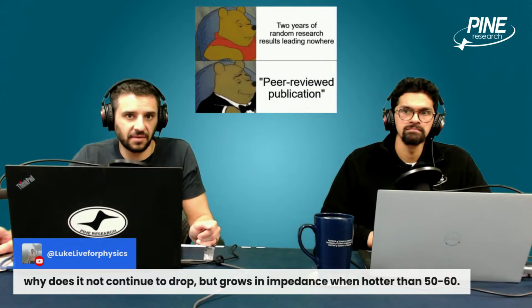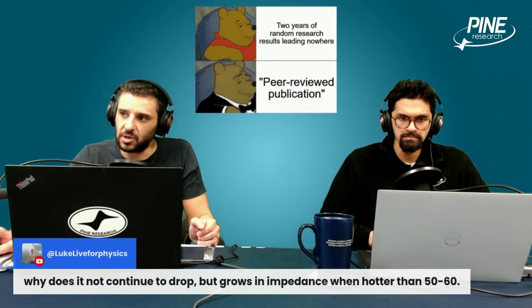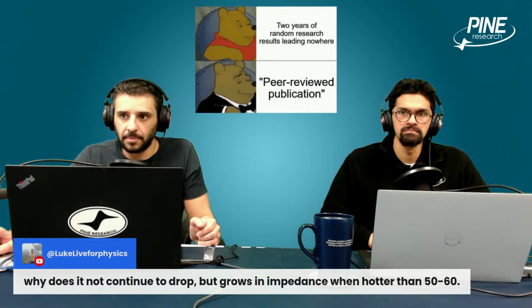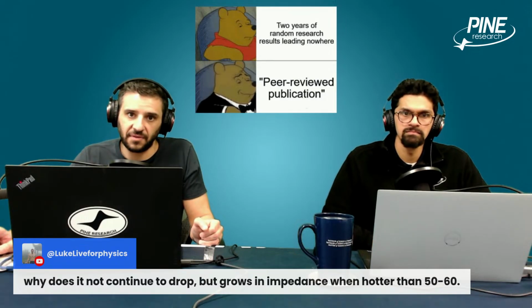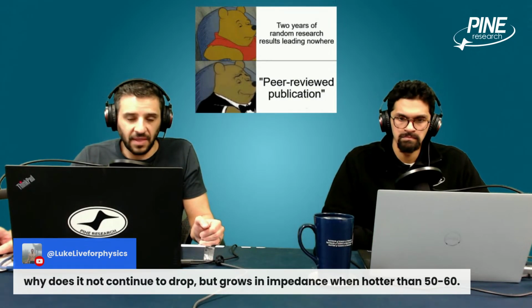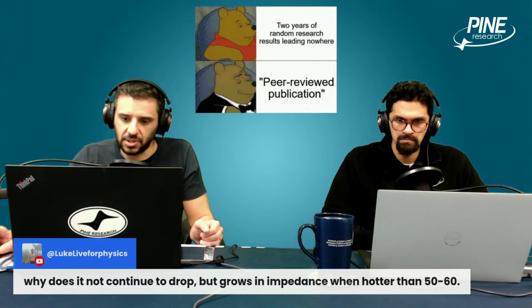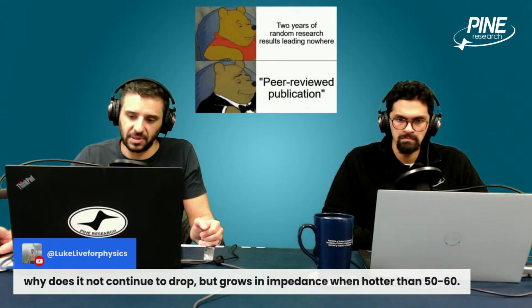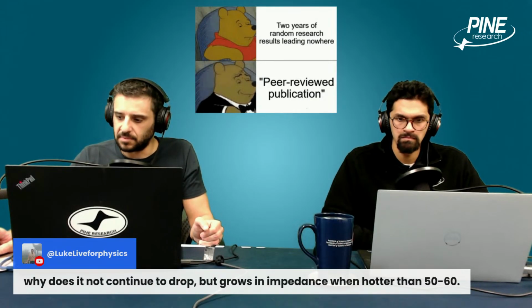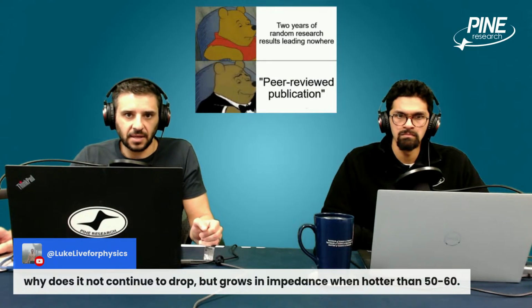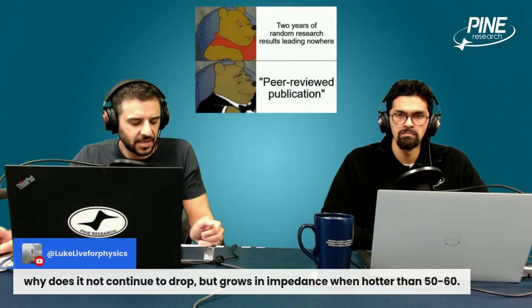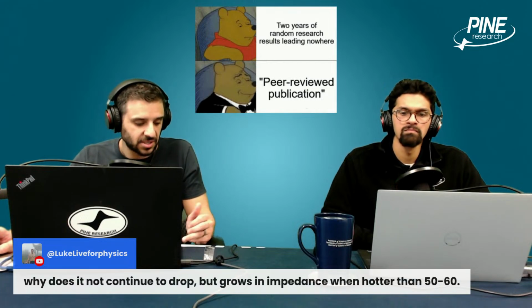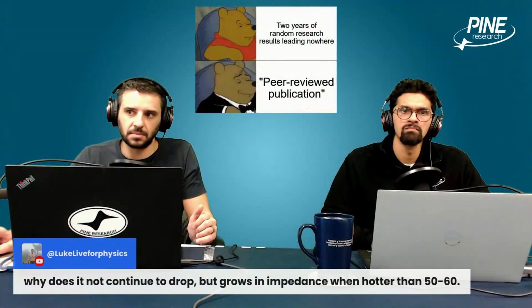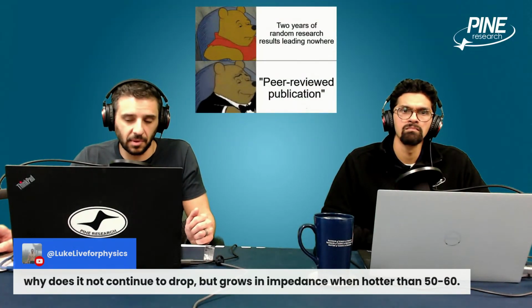you caused a lithium plating event to occur, you caused a dendrite to form, maybe you caused the separator to partially dissolve or fuse, you created a soft or even a hard short, and then all of a sudden your battery might die. Short circuit, 0 volts, at worst case, a safety feature. Hopefully they have built-in safety features like a PTC or CID, something like that. And very worst case is the battery itself will experience a catastrophic thermal runaway event.